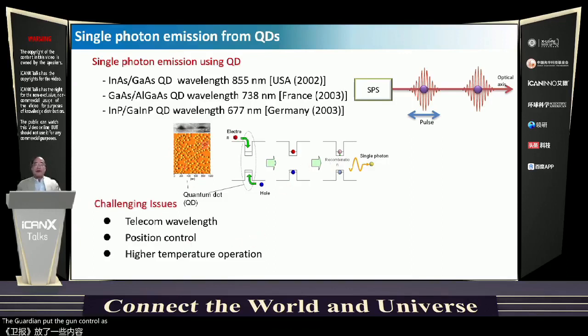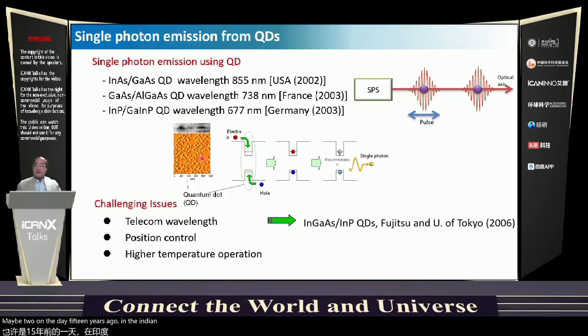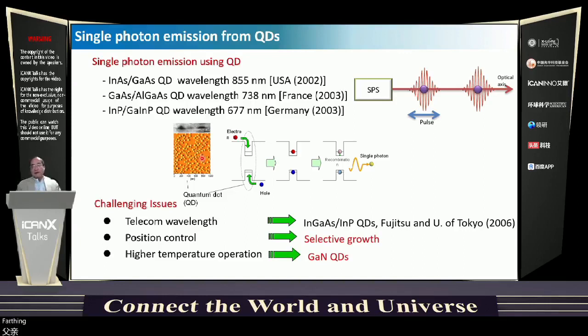Regarding position control, as you know, the quantum dots are randomly distributed, so it is not easy to control the positions. Regarding the telecom wavelengths, almost 15 years ago, indium gallium arsenide indium phosphide quantum dots were realized for single photon sources, and we demonstrated single photon emission at that time. Position control can be solved by using selective area growth, and high temperature operation can be solved by the gallium nitride quantum dot structures. So here we focus on the topic of the high temperature operation together with position control.